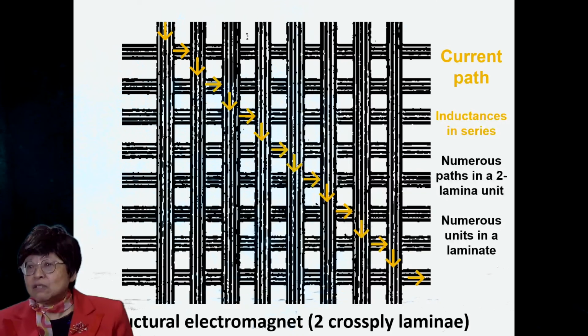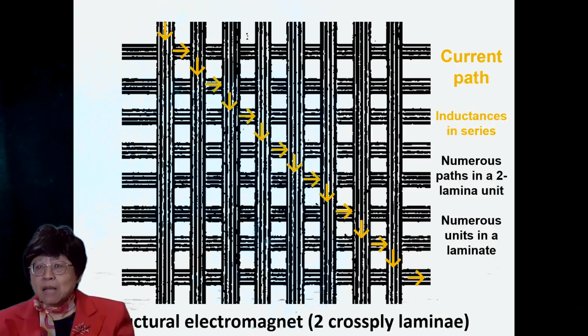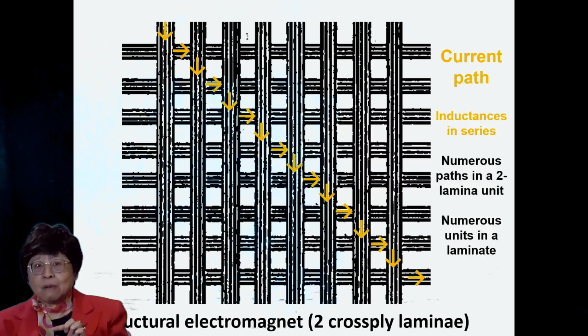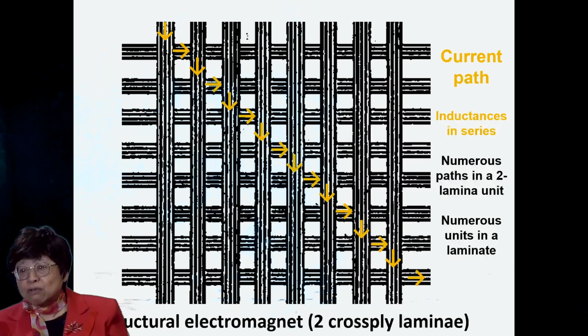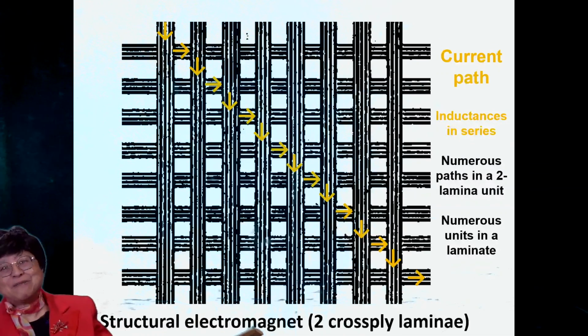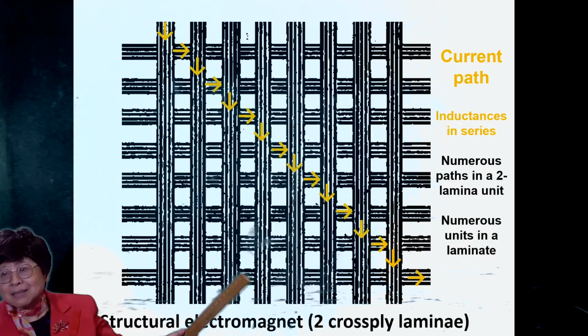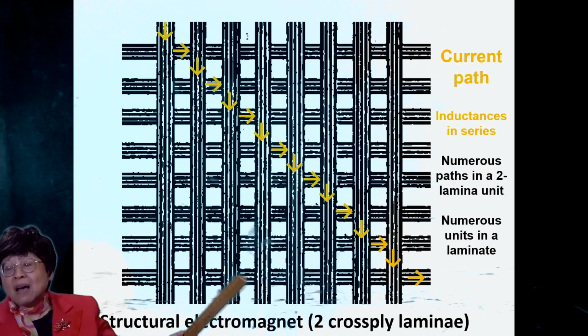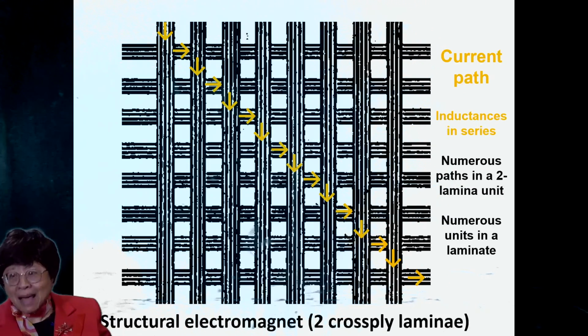And one is not limited to one such current path. There can be many different such current paths, maybe parallel to one another for the same two-lamina unit. And we can have multiple two-lamina units in the same laminate. So potentially one can build up the inductance quite a bit. And the inductance means the capacity to make an electromagnet. So we are envisioning structural electromagnet, which is a term that I invented, that is using a structural composite, actually without modification, to be an electromagnet.